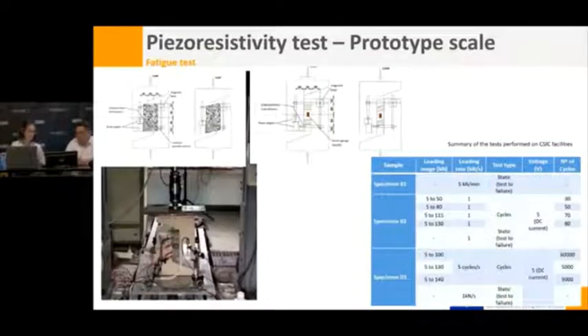Other equipment used for the mechanical testing was displacement transducers, those here, and also a strain gauge rosette for the strain measurement, and displacement transducers to measure the displacement and the slip between the mortar faces. Here in the table, you have a summary of the tests performed here in the CSIC facilities. I think on Friday you are going to see those labs. We made first the push-out test to check the shear bond strength. Later on, we made a cyclic test, and finally, we made a fatigue test.